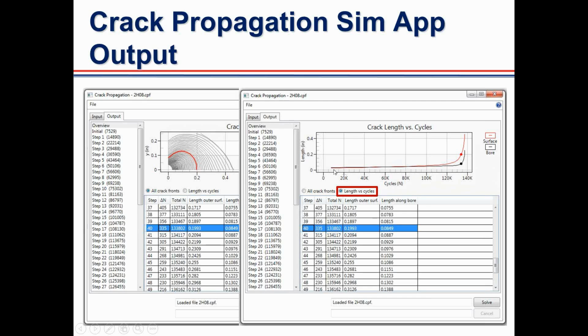What is interesting to note, which is a problem from the point of view of inspection of the cracks, is that the crack remains fairly small for a long time, and then all of a sudden it starts to grow very rapidly. So the precise and accurate computation of these curves is important because that defines the inspection interval to catch the crack before it becomes critical.